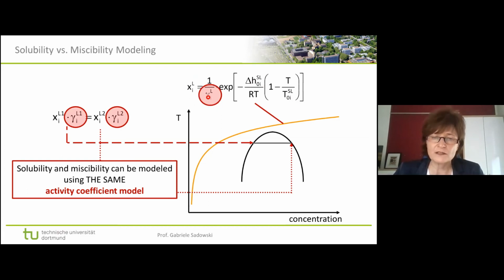This property is a liquid property. So this refers to the interactions between the dissolved molecule and the solvent molecule. And that means that this property does not know what the crystal lattice is, because this is a liquid phase property. And this is very nice, because the equation of state parameters are parameters for describing the liquid properties. So we can use any polymorph of a substance to determine its parameters. And once we have these parameters, then we can even predict, I don't have a slide at the moment, but we have several of these examples and all of them work. So if we then go to a different polymorph and somebody gives us the melting properties of the other polymorph, we then can predict what the solubility of the other polymorph is. So this works quite nice.